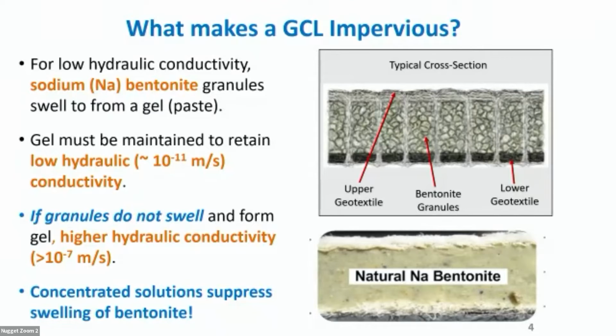And what's particularly important is that the swelling of these tends to be suppressed in high ionic strength solutions or concentrated solutions. Also, solutions rich in divalent cations or polyvalent cations will also suppress swelling, things that we would commonly find in a heap leach solution.